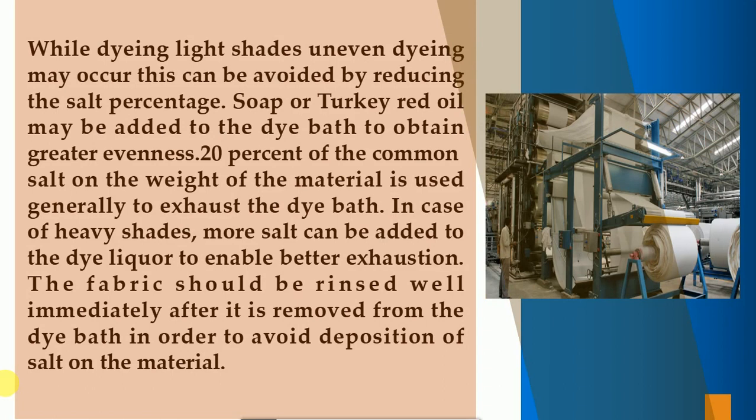While dyeing light shades, uneven dyeing may occur. This can be avoided by reducing the salt percentage. Soap or Turkey red oil may be added to the dye bath to obtain greater evenness. 20% of common salt on the weight of the material is generally used to exhaust the dye bath. In case of heavy shades, more salt can be added to the dye liquor to enable better exhaustion. The fabric should be rinsed well immediately after it is removed from the dye bath in order to avoid deposition of salt on the material.